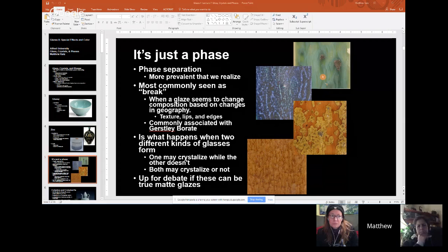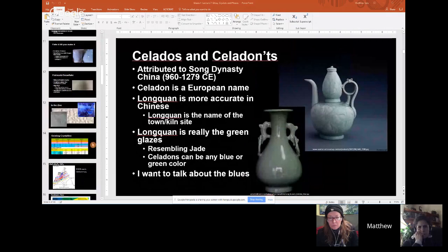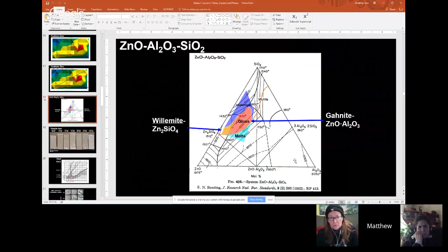The same way with, theoretically, you could say the crystalline glazes are phase separated because, to be clear, which I think, did we have that? Yeah. Okay. So we had that in this lecture too, where what's going on is that, remember, crystalline glazes are existing within the glossy region. That's what's really odd about them. From a compositional perspective, they are glossy glazes. But because zinc in the proper conditions will nucleate and grow crystals, it will make crystals.